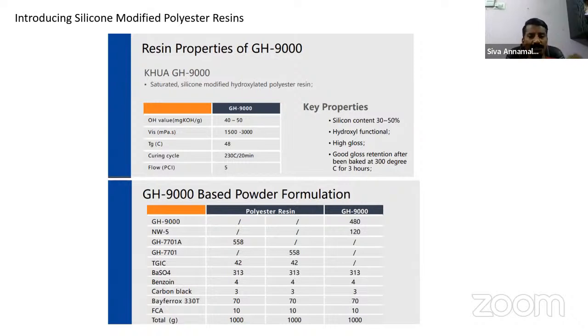So we picked up this resin. We developed it last year, but we commercialized it last May, in technical collaboration with one European company. So we compared this product with the existing high viscous polyester resin currently used in the industry for high temperature performance to the tune of 300 degrees Celsius. So GH9000 is basically silicone modified polyester, and